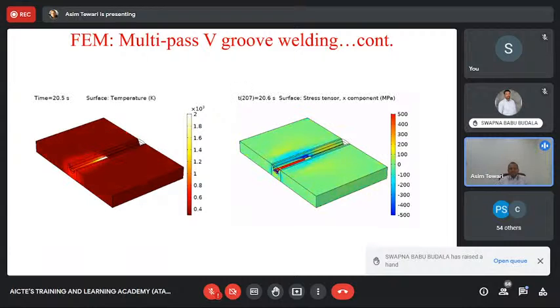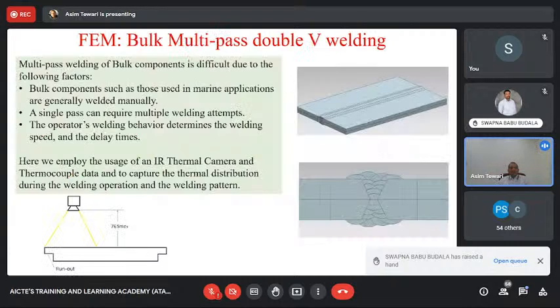on individually added sections. Now for this, what we did was that we performed actual experiments in bulk V grooves, and we added the material in a welding process. And this is probably the most, I would say, authoritative experiment where we were actually adding welded material step by step and keeping track of how that welded material is changing the temperature, the distortion and stresses and everything. So what we did in this case was that we constrained the plates from the side, and we had thermocouples all over the place, which could measure the temperature at different locations of the base metal.